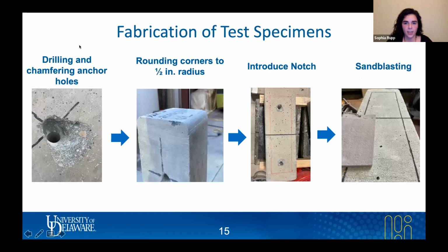Before I could actually get into the actual strengthening of the concrete beams, there were a few steps that I had to take in order to prepare the beam for strengthening. As you can imagine, for the beams that had anchors installed, I had to drill holes into the beams. And not only that, but I also had to chamfer those holes to avoid stress concentrations when the fiber splay anchor was bent over that corner. And for the same purposes, I also had to chamfer the corners of the beams.